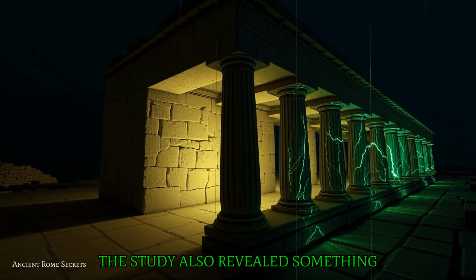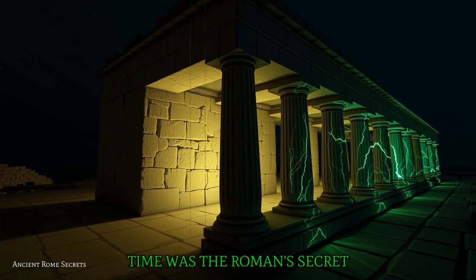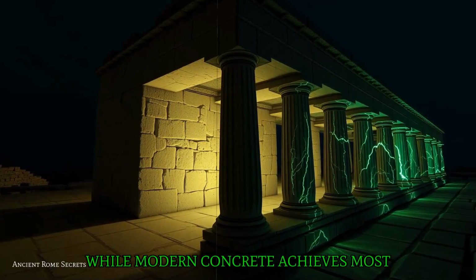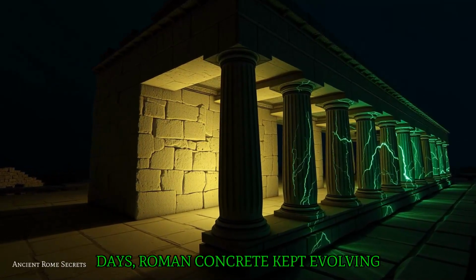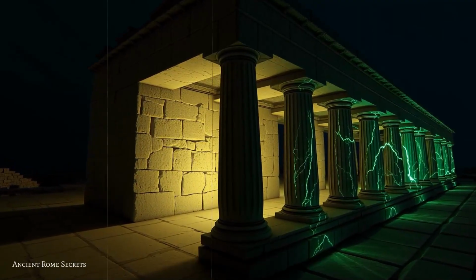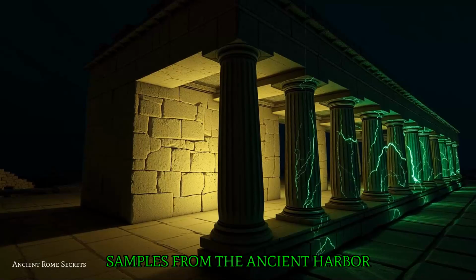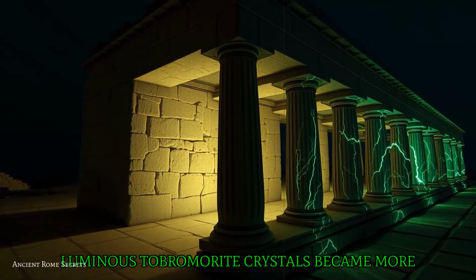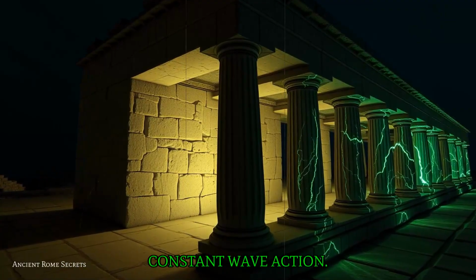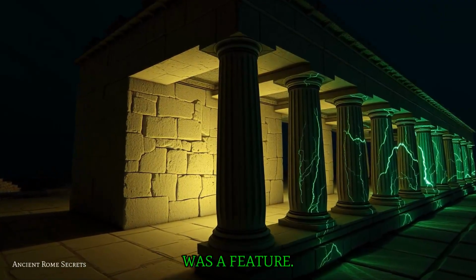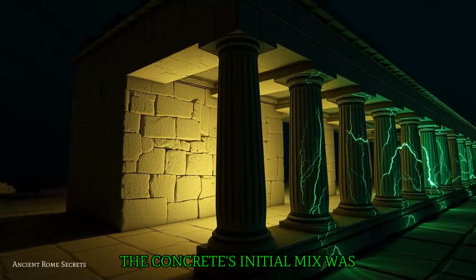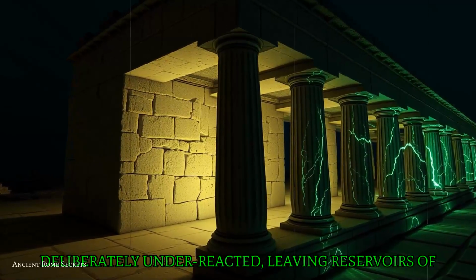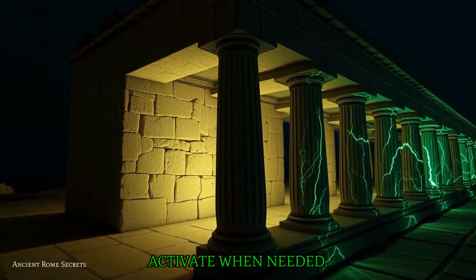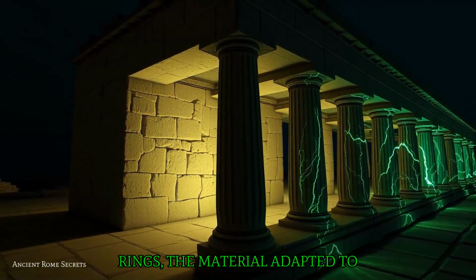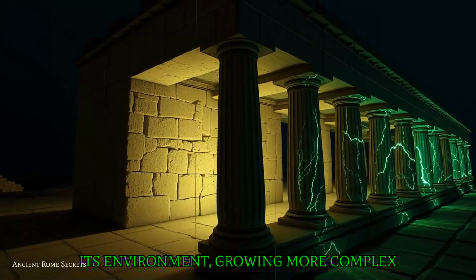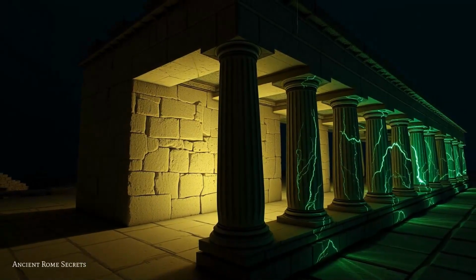The study also revealed something even more counterintuitive. Time was the Romans' secret ingredient. While modern concrete achieves most of its strength within 28 days, Roman concrete kept evolving for centuries. Samples from the ancient harbor of Portus showed that aluminous tobermorite crystals became more abundant in areas exposed to constant wave action. This wasn't a flaw, it was a feature. The concrete's initial mix was deliberately underreacted, leaving reservoirs of lime and silica that could activate when needed. Like a tree adding growth rings, the material adapted to its environment, growing more complex and resilient with each passing decade.